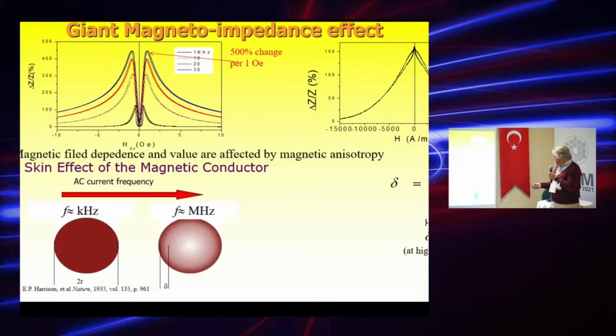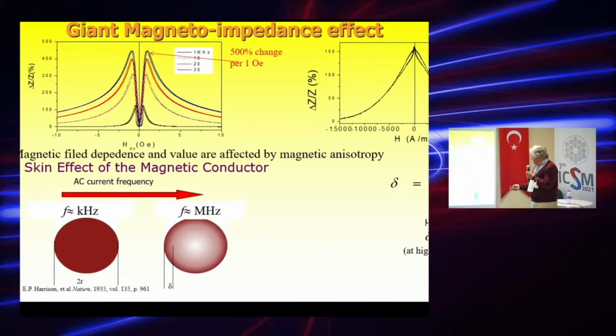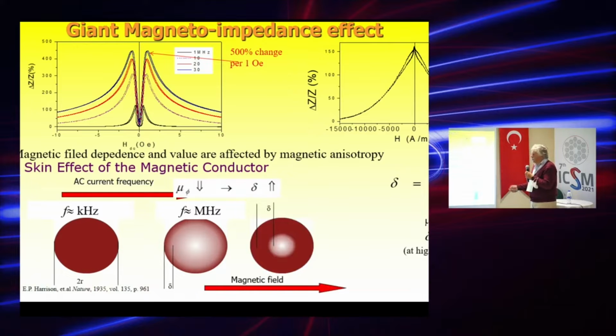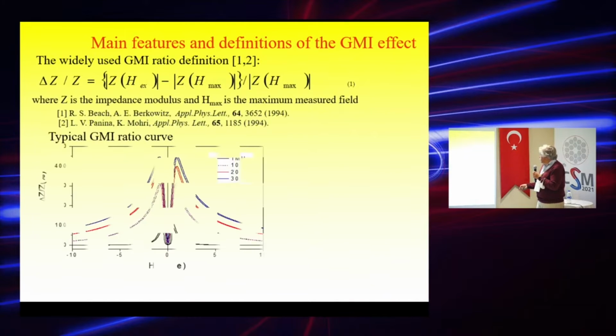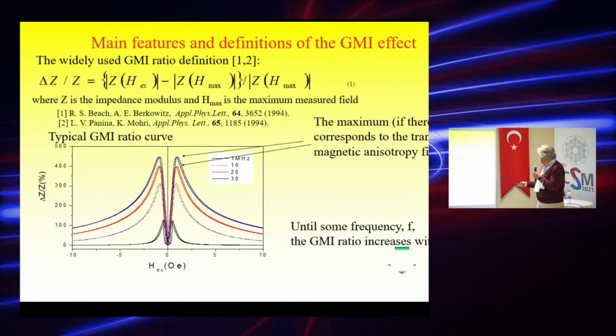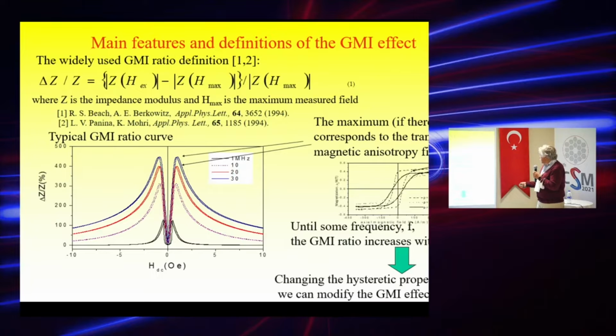In the general picture, this is the cross section of the microwire. We increase the frequency, the current now flows near the surface, and then if you apply a magnetic field, you can change the sample impedance, because the area in which the current flows changes under the effect of the external magnetic field. It is important that this effect is essentially related to the magnetic softness of the materials. The GMI performance is affected very much by the hysteresis loop of the material. So if you are able to achieve very soft magnetic materials with high permeability, we can probably enhance the giant magnetic impedance effect, and this is what we pursued in this group.